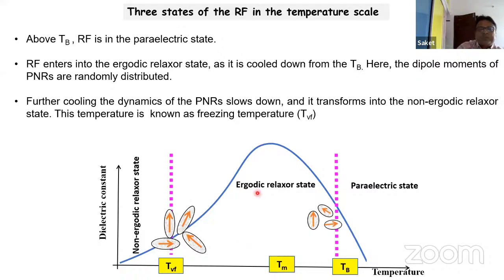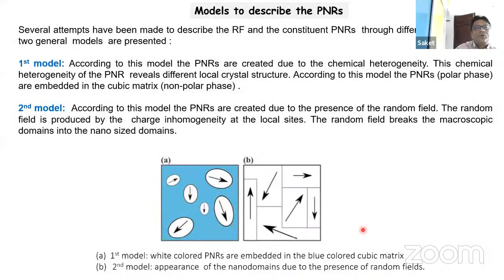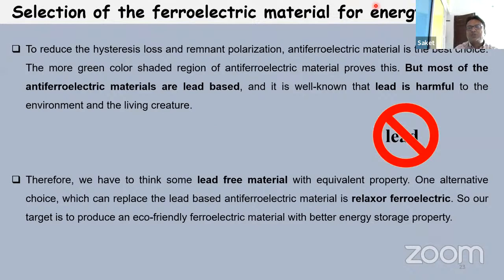So there is a formation of nanopolar regions, and these regions will have different critical temperatures, different transition temperatures. That's why you can see a distribution of the transition temperature. That's why we get the diffuse phase transition. For the relaxer it is a diffuse phase transition. This I can skip because it is a related model to the polar nano regions. This I already mentioned. This is just for reading purposes if you want.